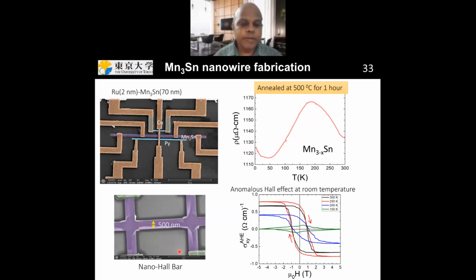Because people who have already fabricated Mn3Sn know it's very difficult to make a thin film. And if you want to make a nanowire, it is much more difficult, because most nanowires, even if you make a completely stoichiometric nanowire, will oxidize very, very quickly. To optimize this device, it took almost 1 year. But in the end, we could fabricate very good quality Mn3Sn polycrystalline nanowires.